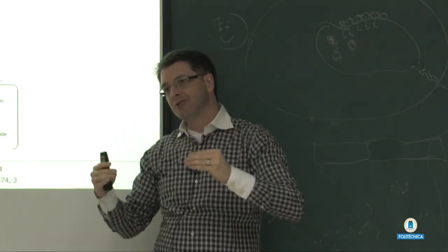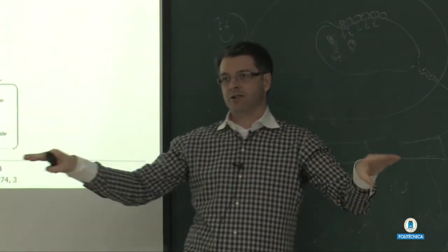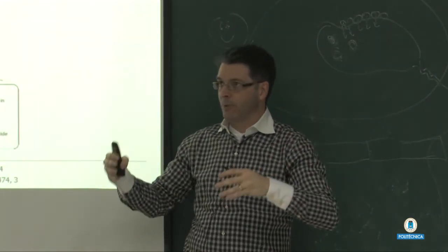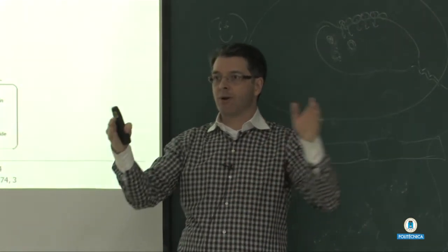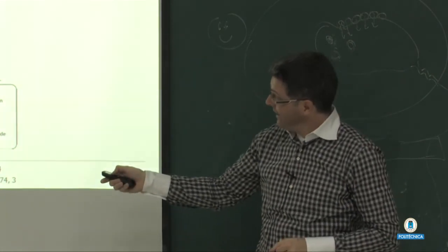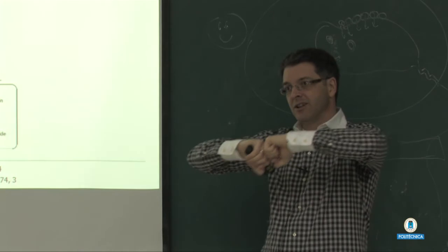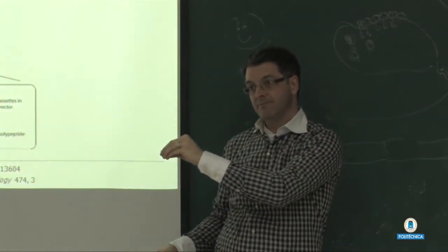So what we tried to do, that was sort of the idea. We remove everything that's non-functional. And as a result, of course, we wanted that to happen, but we couldn't predict that it would happen. And everyone else that saw it said it would never be soluble. But indeed, having such a seamless linking of functional units makes the molecules highly soluble.